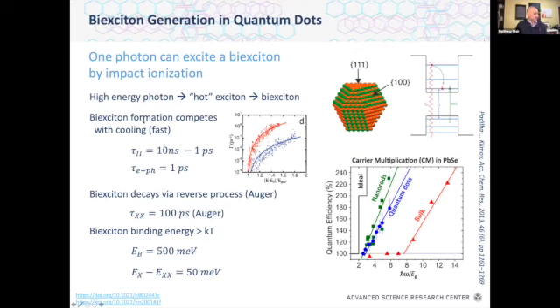What's important to note about biexciton formation, in this carrier multiplication regime, where we've only put one photon into our system, is that the yield of the biexciton is a result of the competition between the normal one electron relaxation process and the impact ionization process, which produces our biexciton. What's really notable in these systems is that the impact ionization rate is strongly a function of the initial energy of your hot exciton. The hotter the exciton, the faster this impact ionization will be. And so the yield of the biexciton is a strong function of the input photon energy. The impact ionization can go from a few orders of magnitude slower than carrier cooling to something on the same order. As we go up in energy, the impact ionization gets faster and faster.